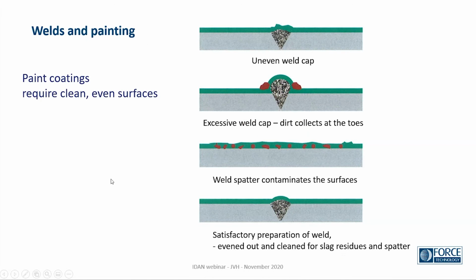Oh yes, just to finish off, the effects of welds on corrosion protection by paint. Some examples: if we have a weld, there's of course the weld cap, which might give an uneven surface on the paint. So if it has been ground, it would be a better surface for the paint. But still, there's protection. But it might lead to contamination or dirt collecting along the weld if you have too high a weld cap, and underneath this the paint might be challenged and corrosion could start.